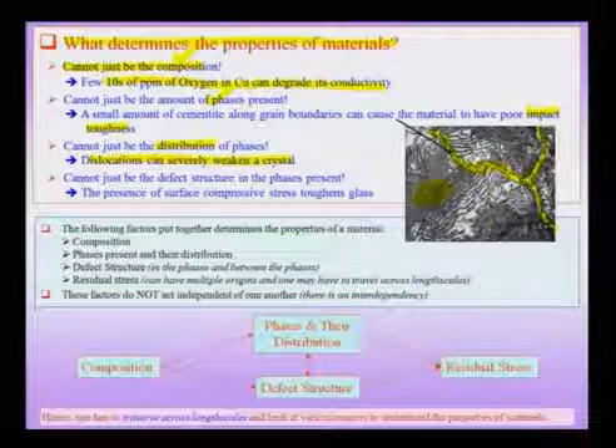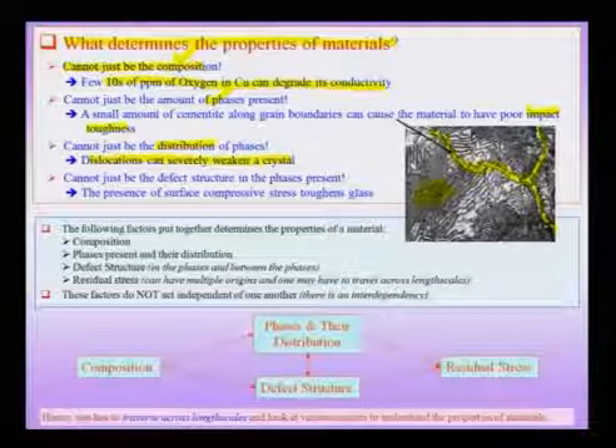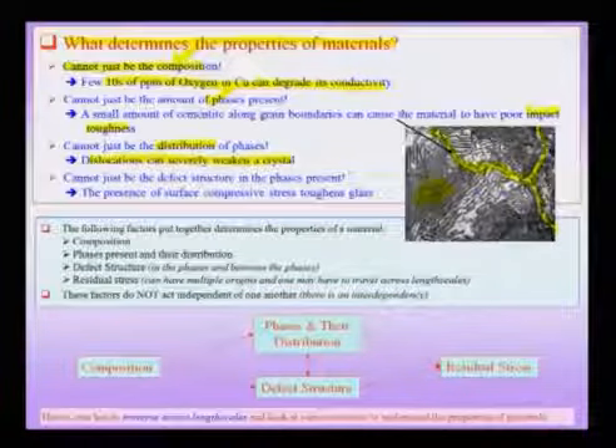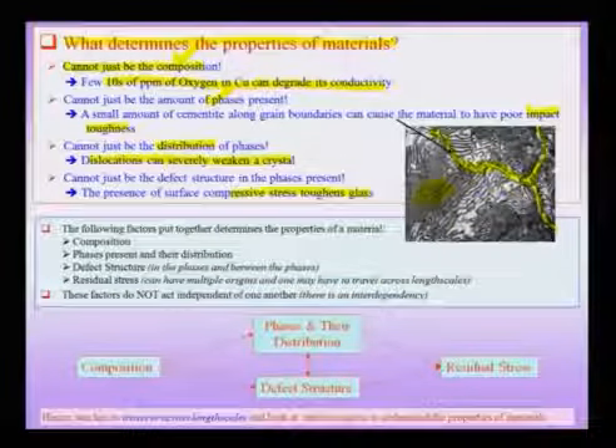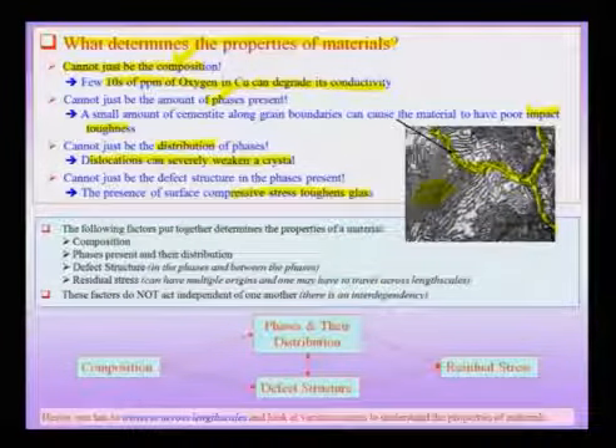But should I stop here? Definitely not. The reason is that we know that normal glass is very brittle and it fractures very easily. If any ball is thrown on a window pane glass, it shatters so easily. But we have another example of a glass which is known as toughened glass. Toughened glass consists of normal glass, but in which there is a certain distribution of residual stresses, especially compressive residual stress on the surface of the glass. This helps to toughen the glass a lot.